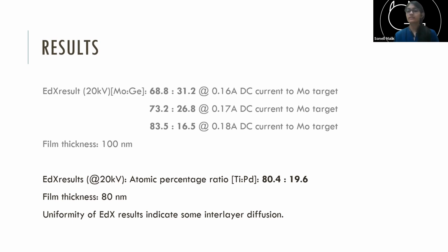But in a lot of cases, it'll be different, because say the argon gas that I'm using, if it is not as pure as what was used in some other paper in some other lab, my transition temperature could be lower. Or if it is more pure than the argon that some other lab has used, I could get a better transition temperature. Or if my vacuum pump is much better than somewhere else, I could get better results. So it's not just thickness, a lot of other things can play a much more significant role in this. So you need to look out for a lot of things.